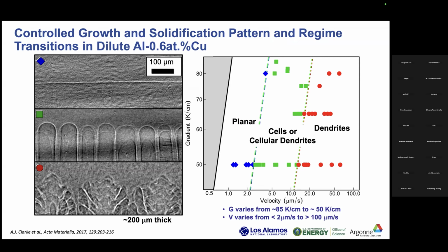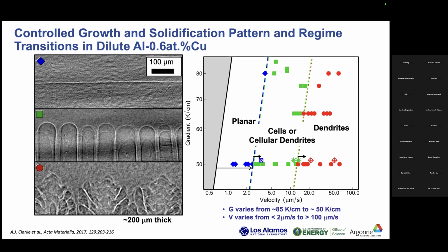And here, the majority of the experiments that we did were bottom-up directional solidification. And what's interesting is solidification theory, this black line here would predict the regime transition from planar to cellular over here, where in reality in experiments, we see it shifted to much higher velocities. So this was a question that we had about why are we seeing higher velocities than we might expect. And so we did a series of very specific top-down directional solidification experiments. And it shows that the velocities we see the growth regime transitions at even shift to higher velocities.